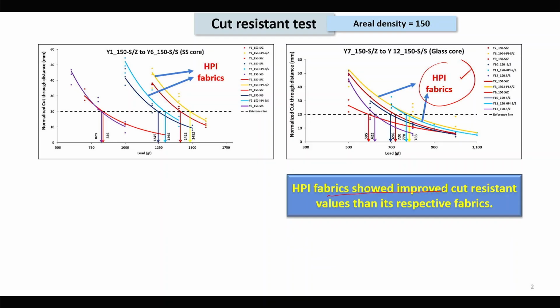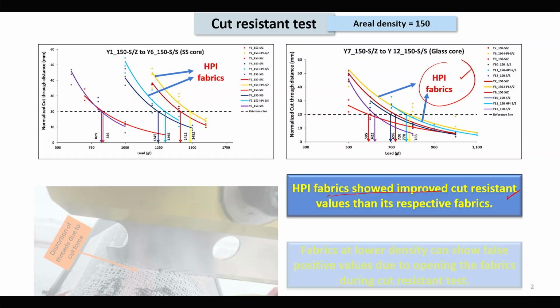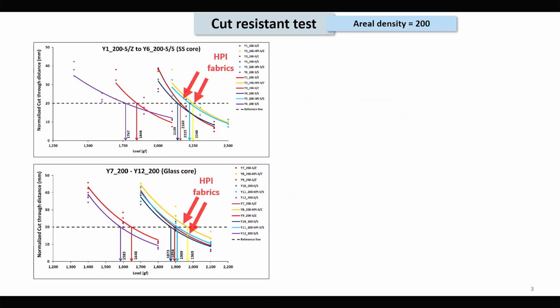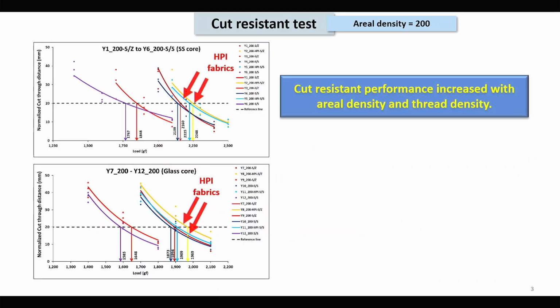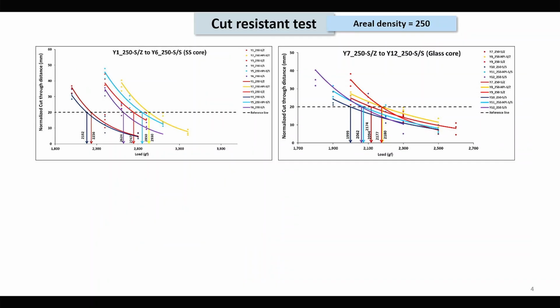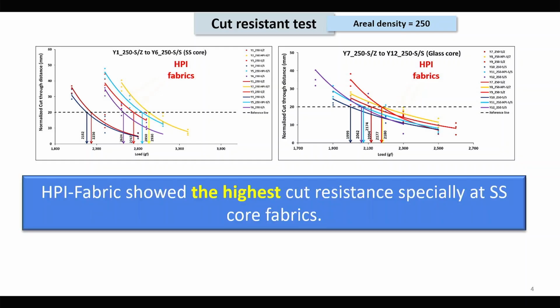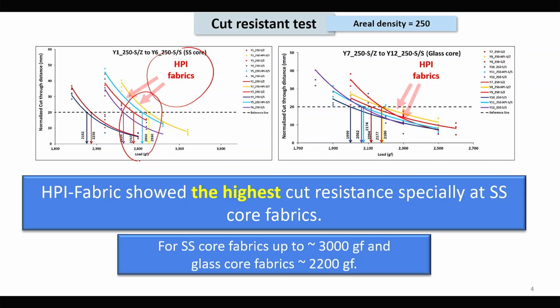So, improved cut protective performance is there with the hard particle impregnated fabric. This is true for all the different areal densities. In 150 GSM we have seen, and also in 200 GSM the cut resistance performance increases and the hard particle impregnated fabric shows the highest cut resistance, that we discussed in the last class also. The same trend is followed in the case of 250 GSM, and the SS core, stainless steel core, gives very high cut protective performance, around 3000, and the glass core fabric around 2200.